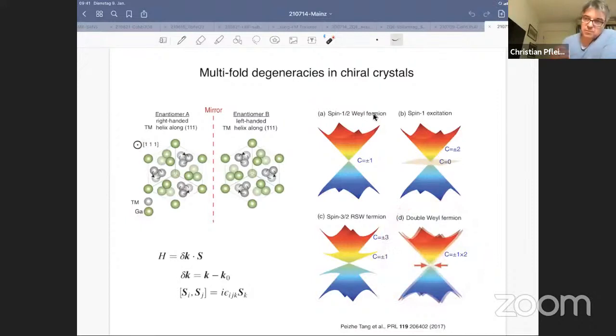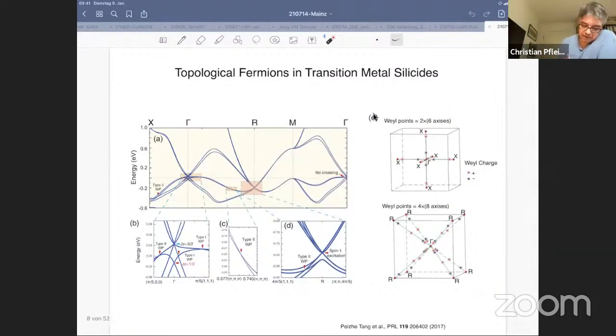One of the issues here is really how important spin-orbit coupling is. The early work already took spin-orbit coupling into account, while in some of the experimental work the interpretations basically argued spin-orbit coupling is so weak that it can be ignored. But we think that there's a huge difference. So here's a picture of the calculation of the band structure for this compound, cobalt silicon.